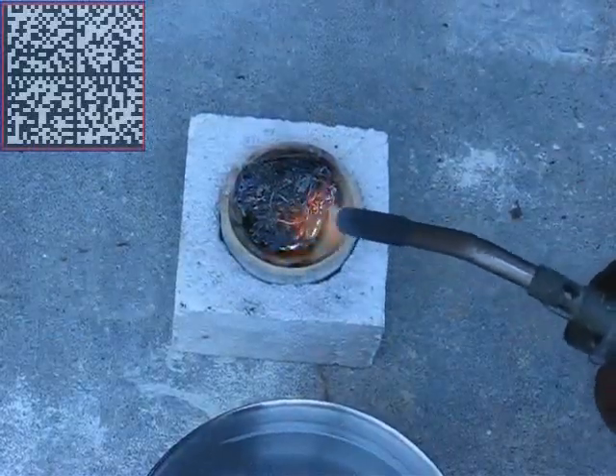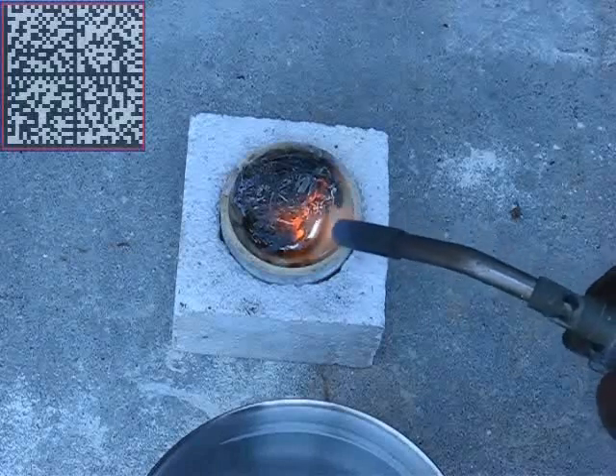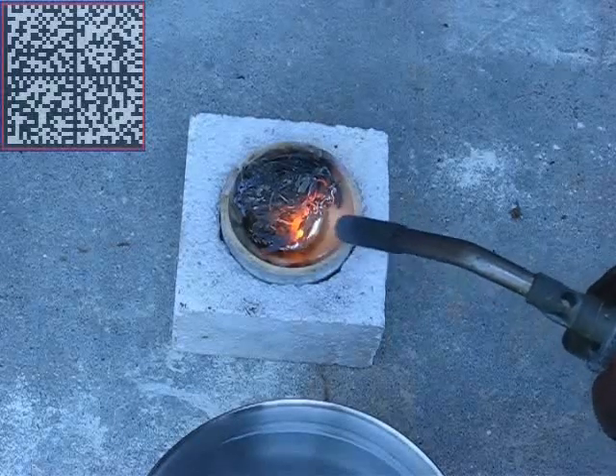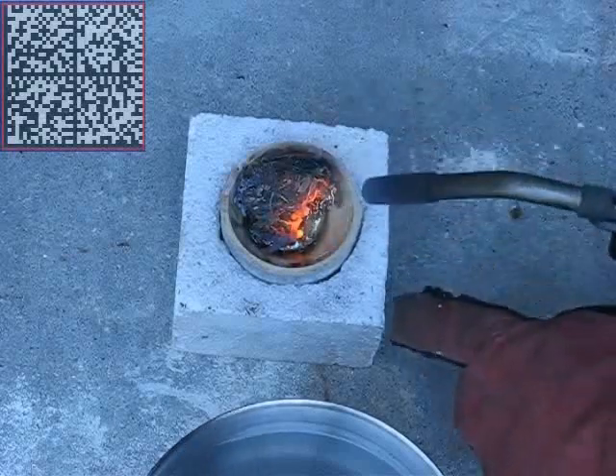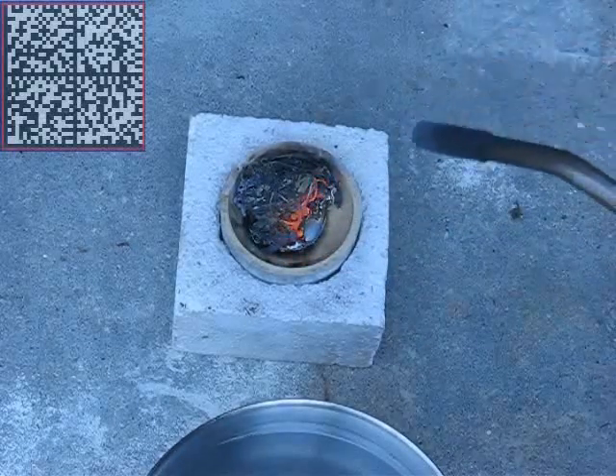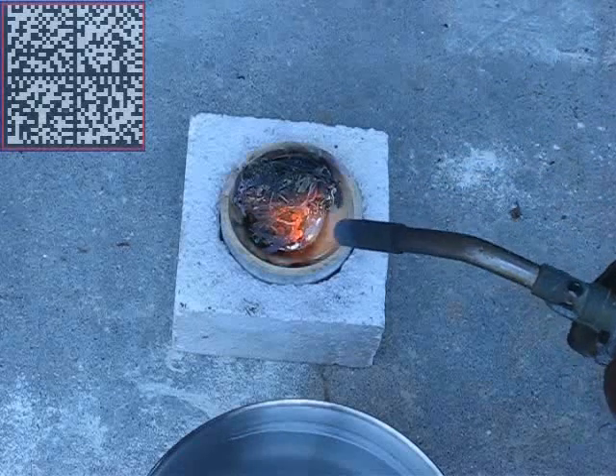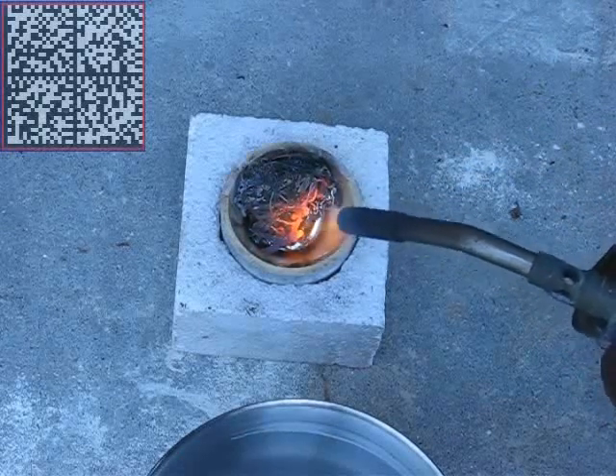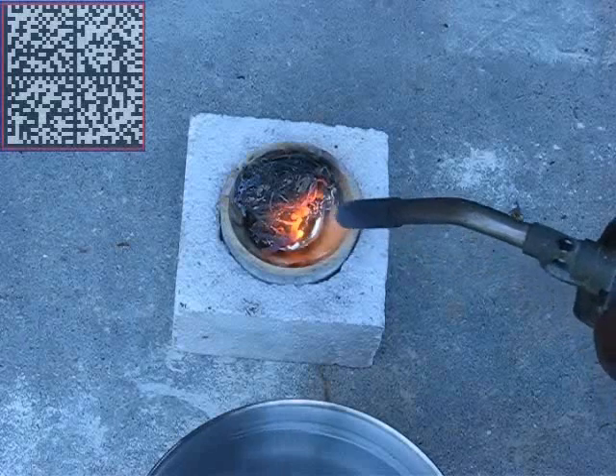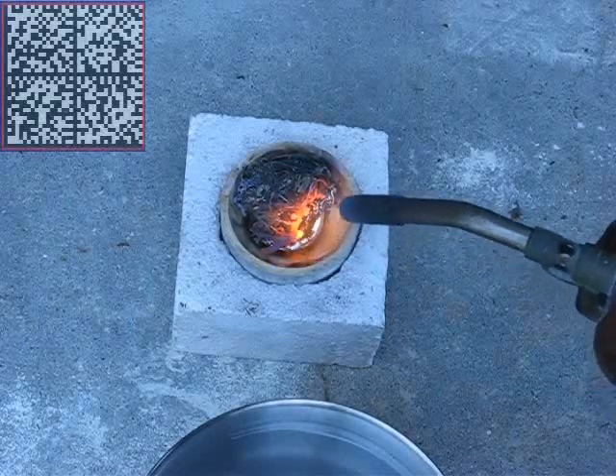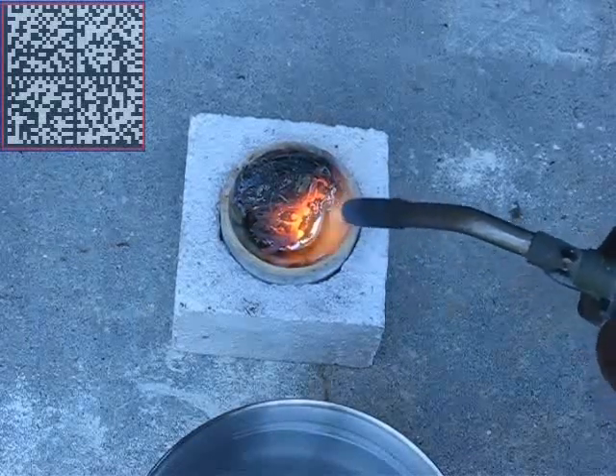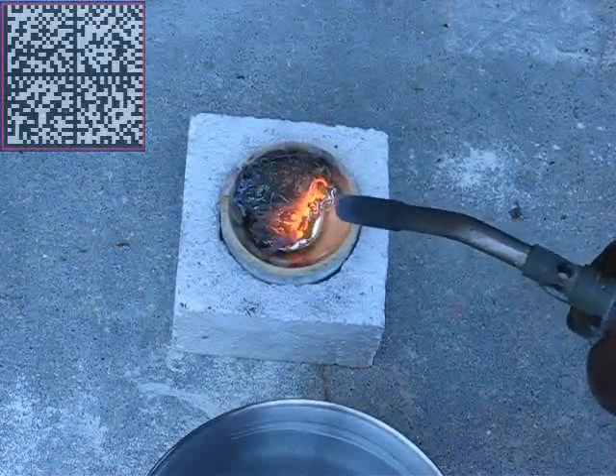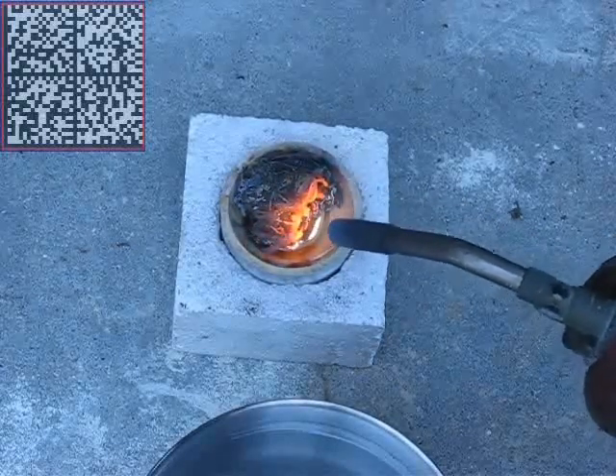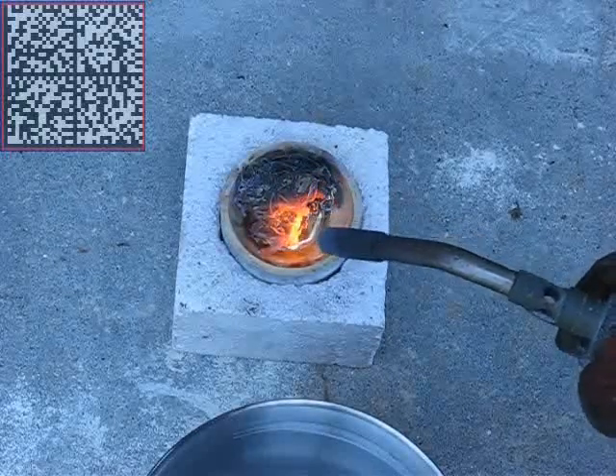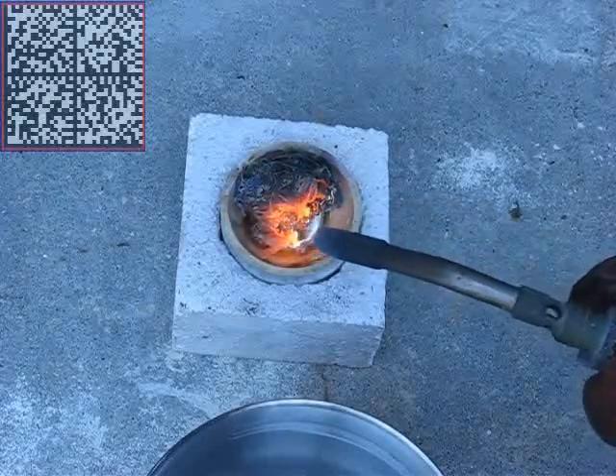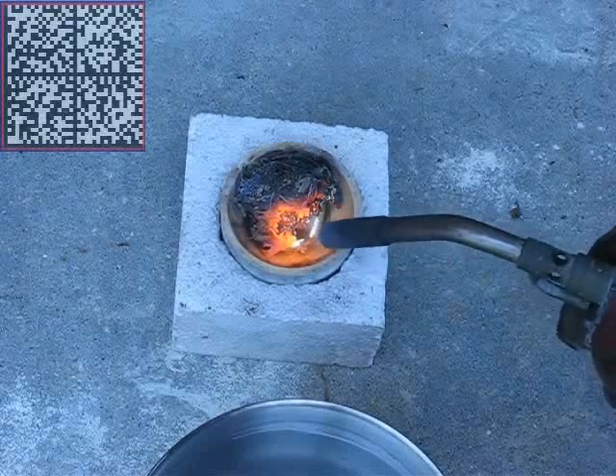As the silver becomes molten in the bottom of the dish, it starts to absorb the gold into it. And if I pull away the torch, you can see the silver looks all shiny in here. When I pull the torch away, it turns into that kind of an off gold color, almost brassy looking. That's a sign that it is combining with the gold, and we know we're making a good alloy. Generally speaking, you want to get the bottom full of molten silver, and as you heat that molten silver and bring the gold to its surface, it'll absorb the gold. We just sit here and work the gold down into the silver, and work our way around the dish, forming the alloy we need for inquarting.